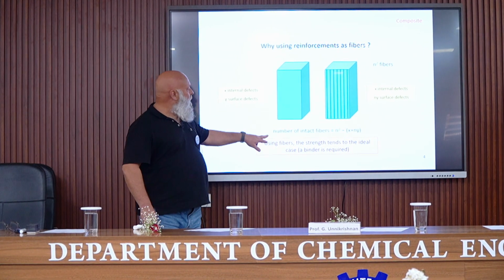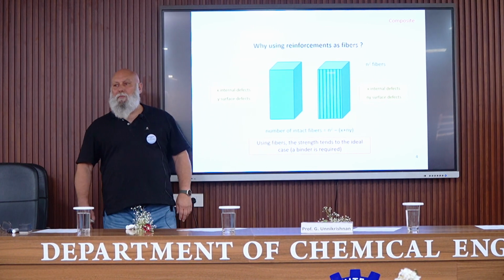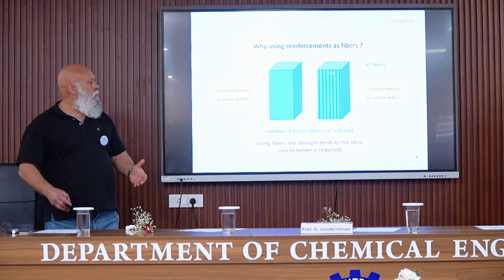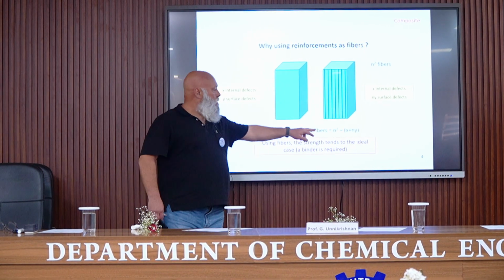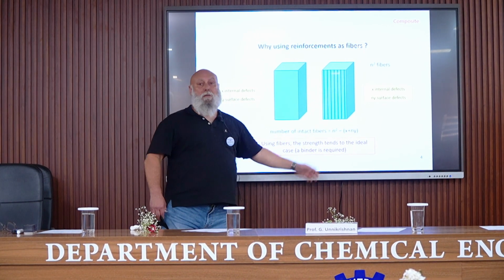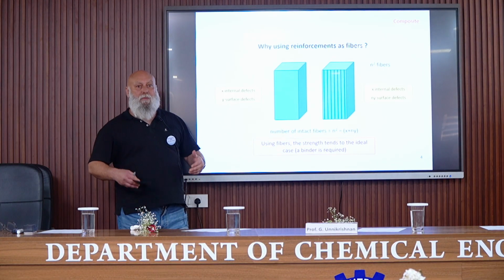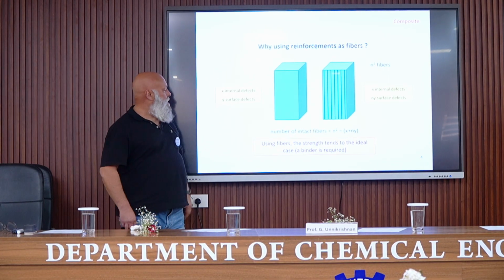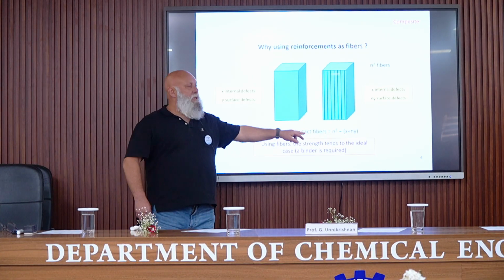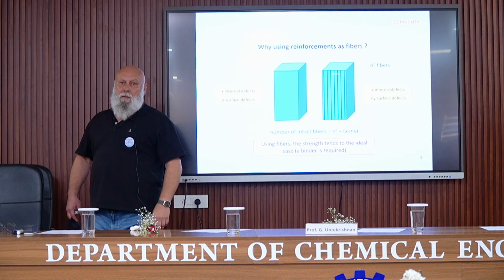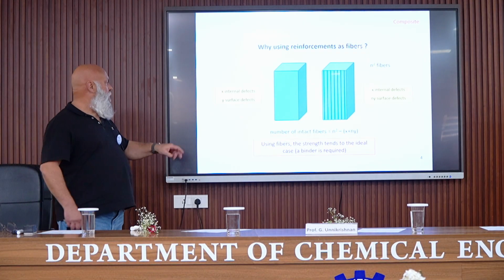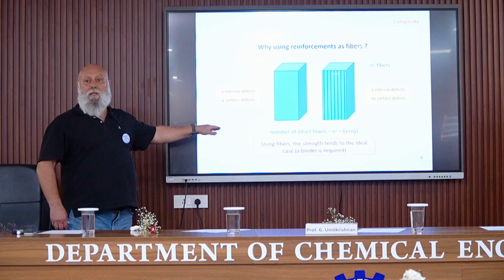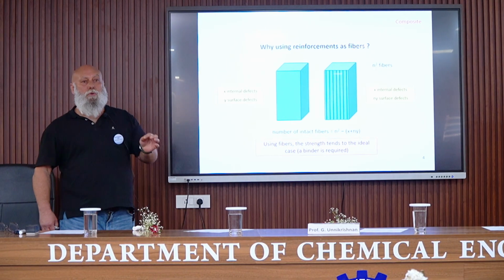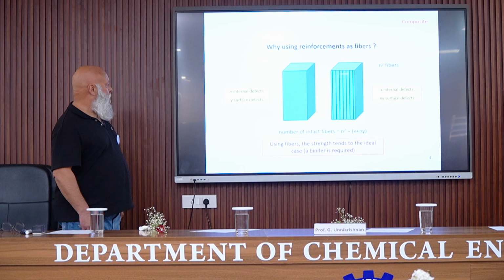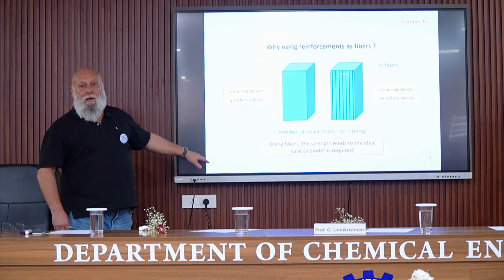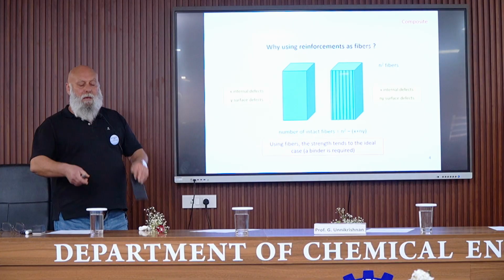Now, when determining the number of intact fibers, so the fibers where you have no defect, it's n squared, the total number of fibers, minus the number of fibers where we have defects, internal or surface defects. And you can see from this equation that by increasing n, we can increase the number of intact fibers. And this is the objective, so it means that it's necessary to use as thin as possible fibers. But of course, it's necessary to have a binder to link these fibers.